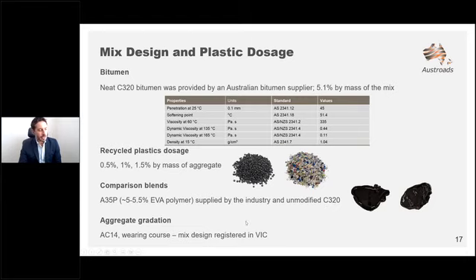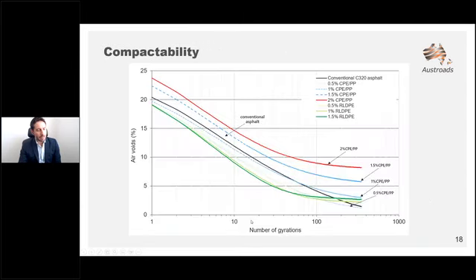The aggregate gradation was that of a wearing course. The mix design was registered in Victoria. The maximum nominal aggregate size was 14 millimeters. This is how the compaction curves look like.